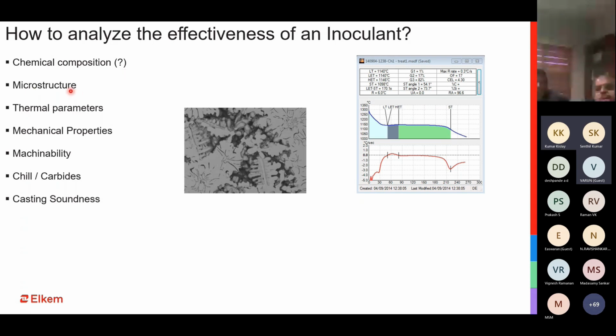A better way of doing it is to look at the microstructure. When you look at the microstructure, you'll have a much better graphite precipitation. You'll have a much better carbon control. You'll have a much better uniformity in your structure. An even more potent and accurate way of looking at it is the thermal parameters. So you look at the thermal analysis, you look at the lower eutectic temperatures, you look at the solidus temperature, you look at the graphite precipitation behavior, you look at the angle towards the end of solidification to see if you have enough graphite precipitation.